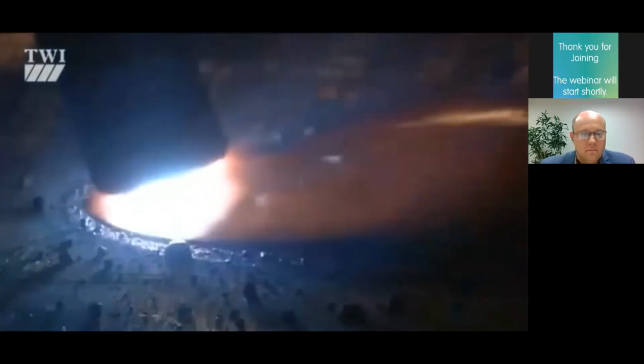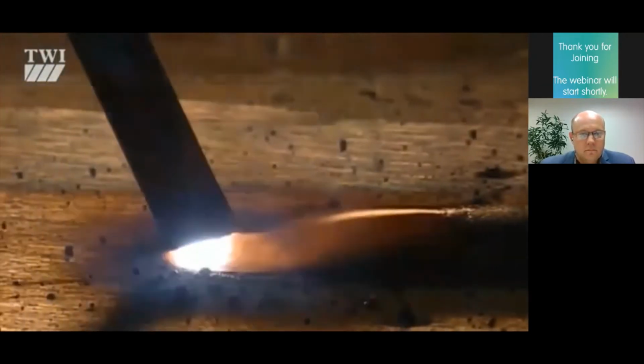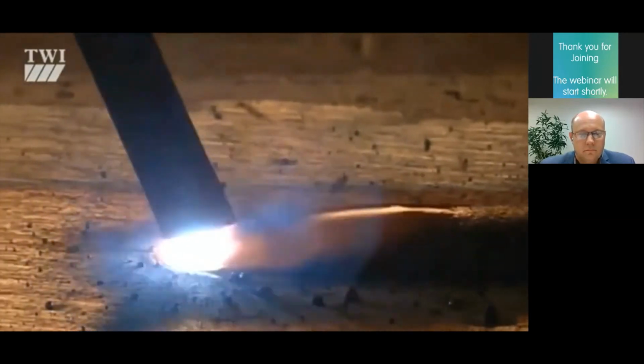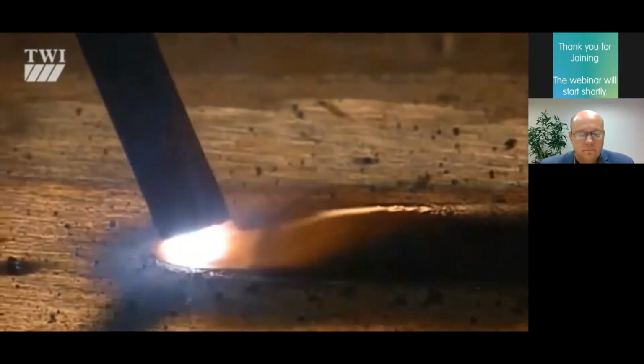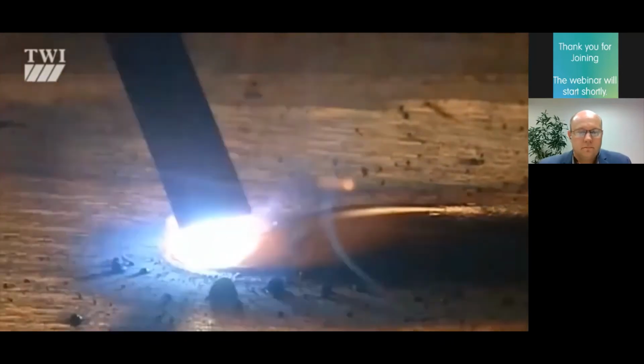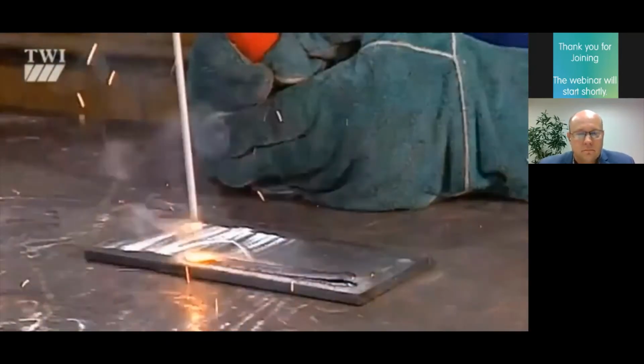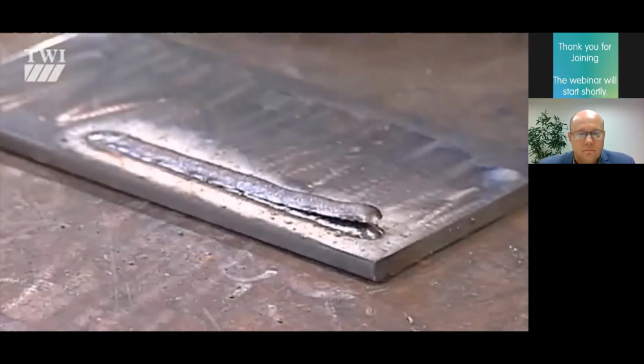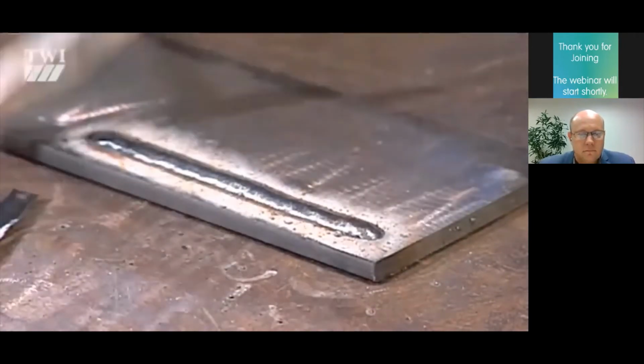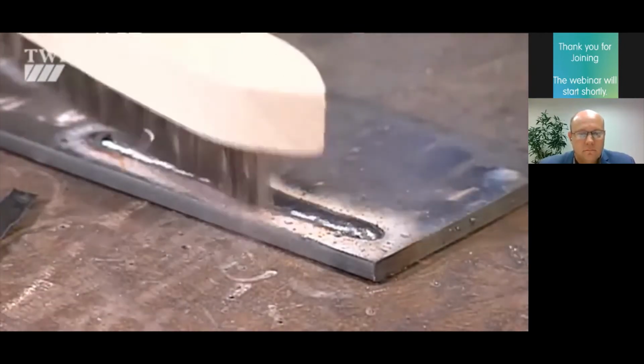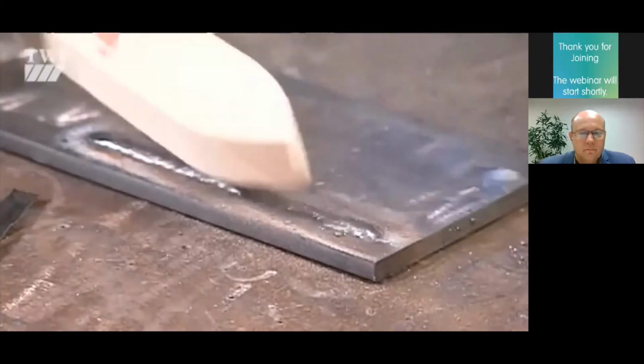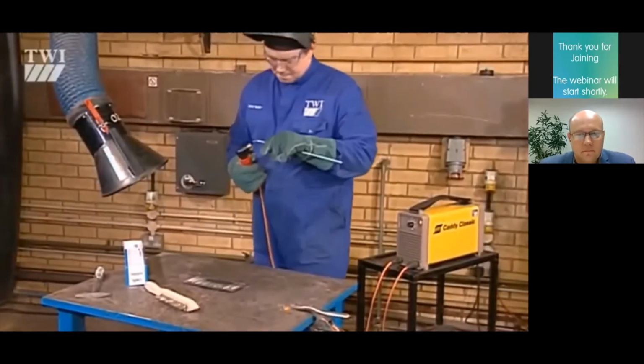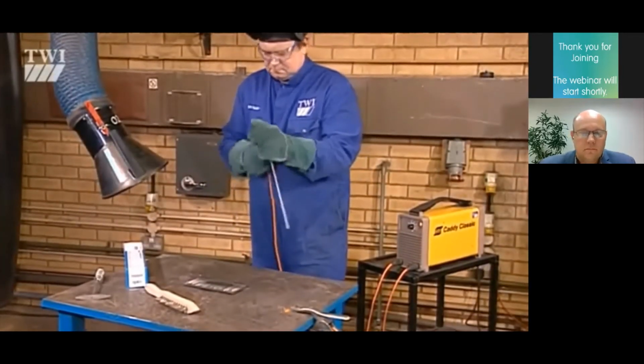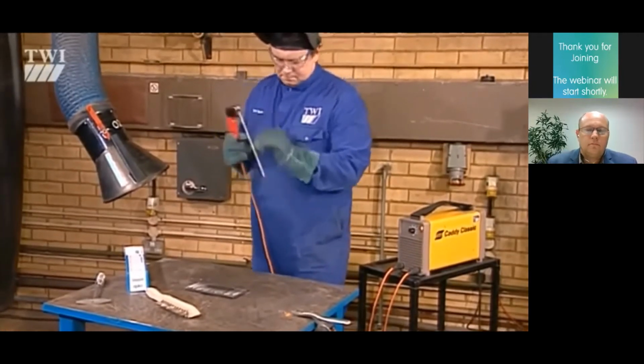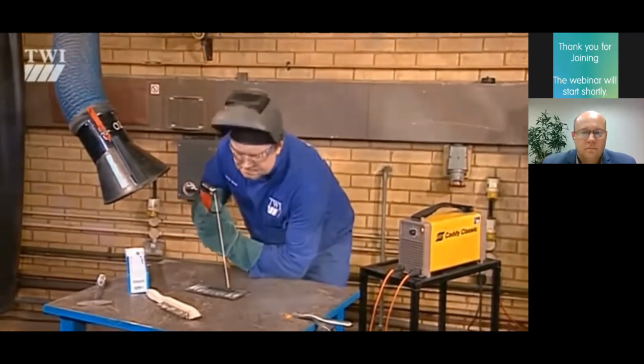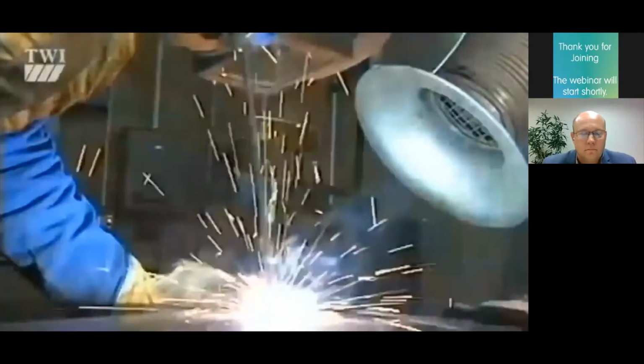The job of the flux, which melts instantly with the electrode and the parent metal, is to form gas and slag, which protects the weld pool from oxygen and nitrogen in the surrounding atmosphere. After welding, the slag cools and solidifies and has to be chipped off. The process allows only short lengths of weld to be produced before a new electrode has to be inserted into the holder.